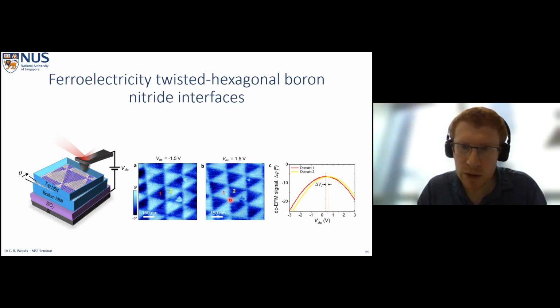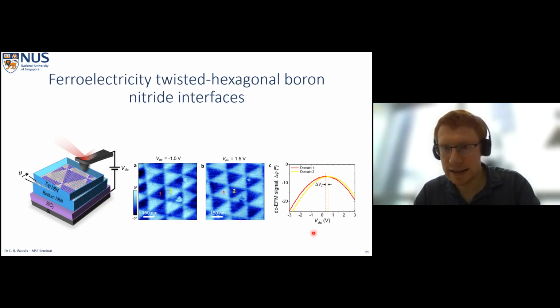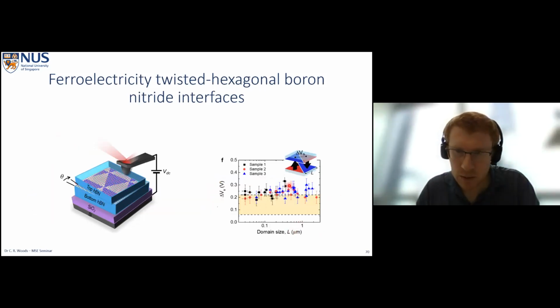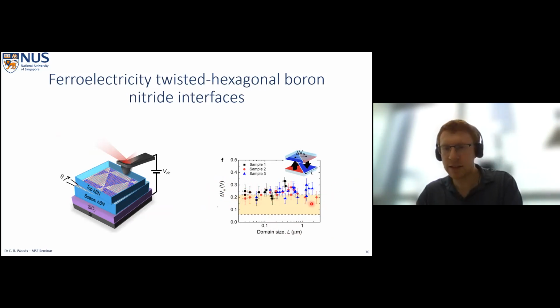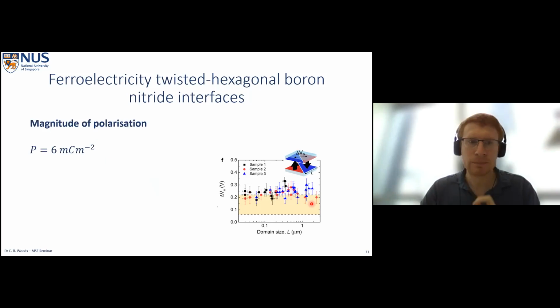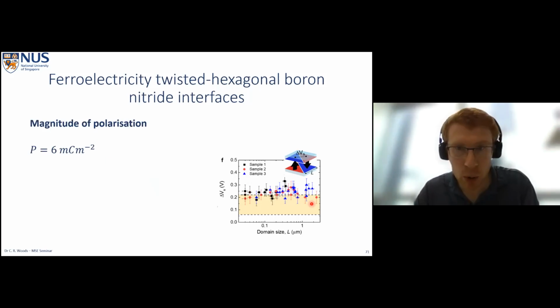And what we find is when we look at one domain, say the bright domain here, 1, versus the dark domain here, 2, the DC voltage we have to put in to get to this 0 force point is different. And when we measure this DC voltage difference between the two domains, we find that it's perfectly uniform when we look at different domain sizes. So we go from the limit of our resolution, which is something like 10 nanometers, all the way up to micron domains, and it's always the same difference in voltage between the two domains. And this tells us that this is not a piezoelectric effect like we saw in the first half, but this is actually a stacking effect to do with the AB and BA stacking themselves. And the magnitude of this voltage corresponds to a polarization across the interface of about 6 millicoulombs per meter squared.